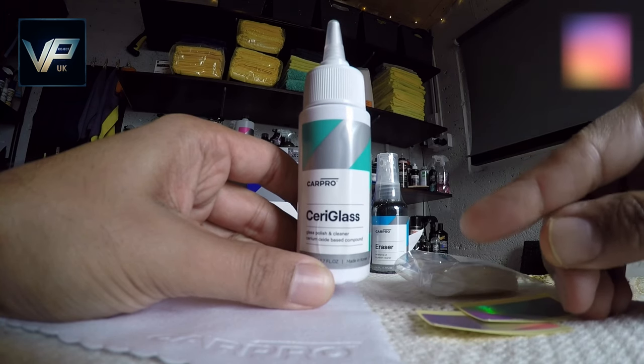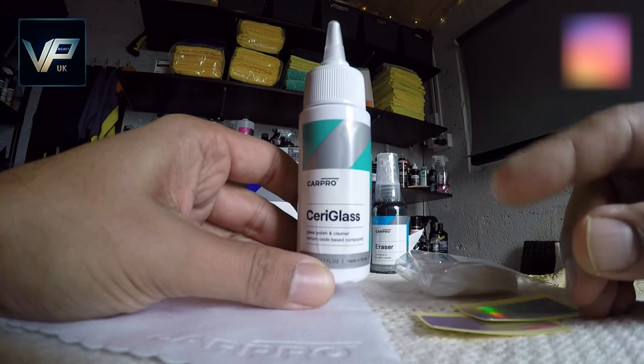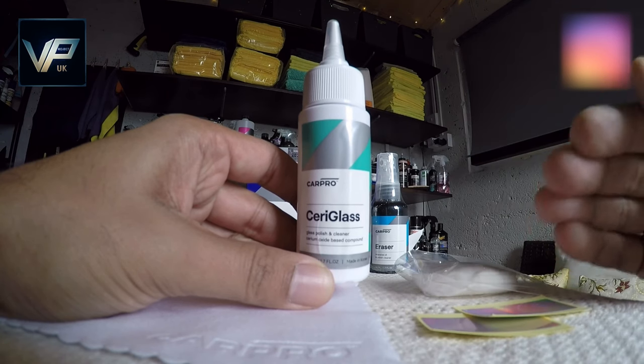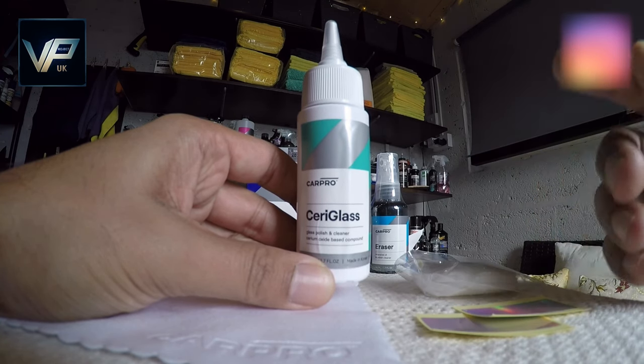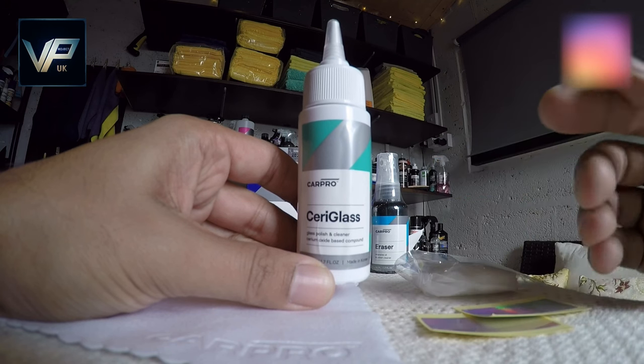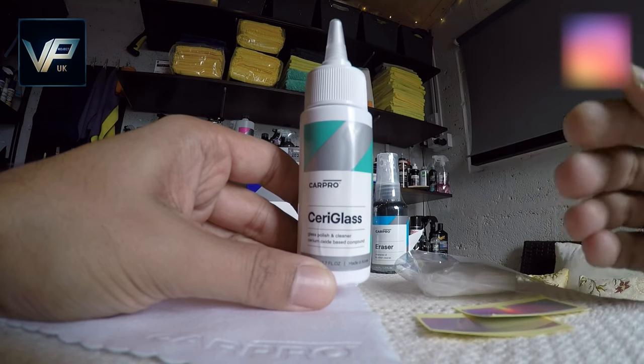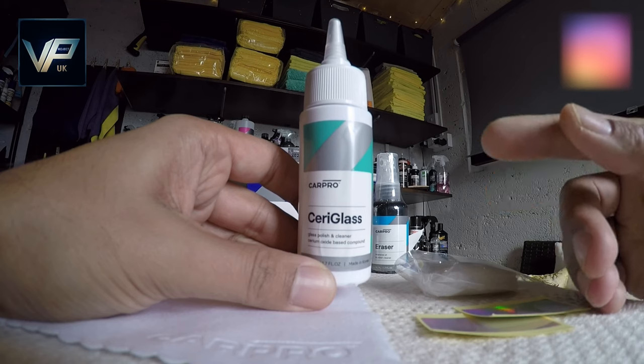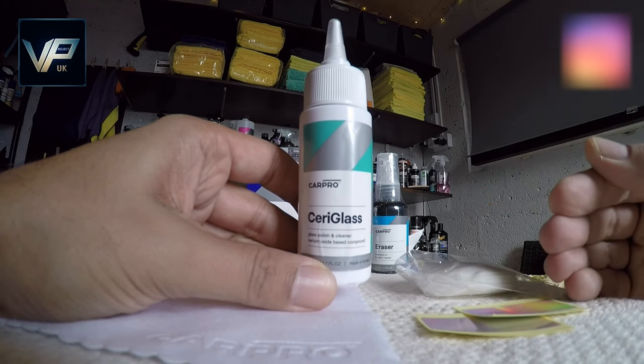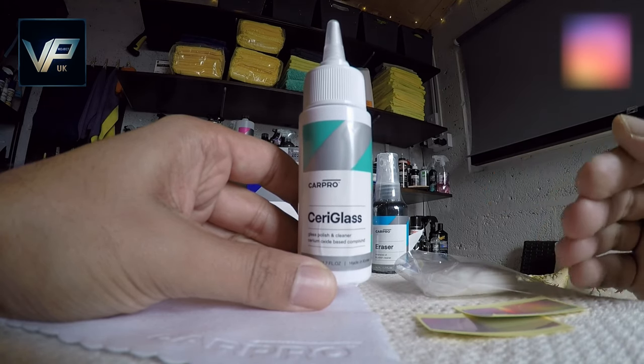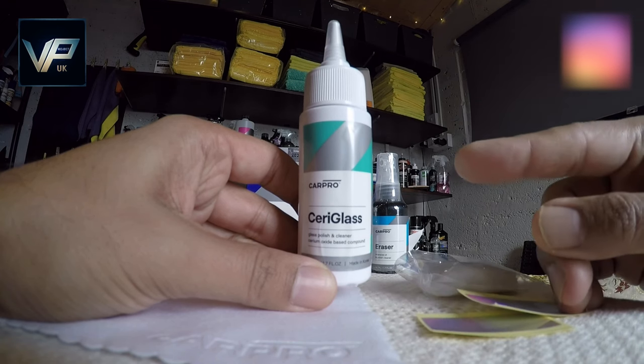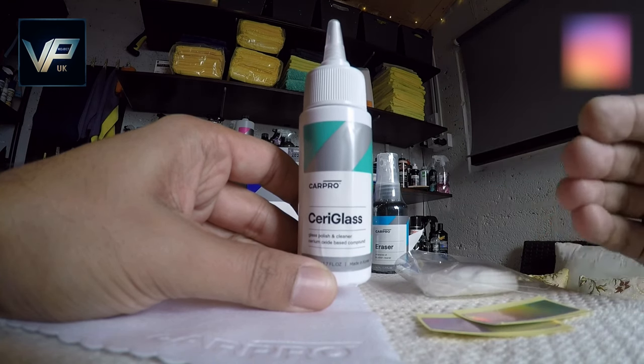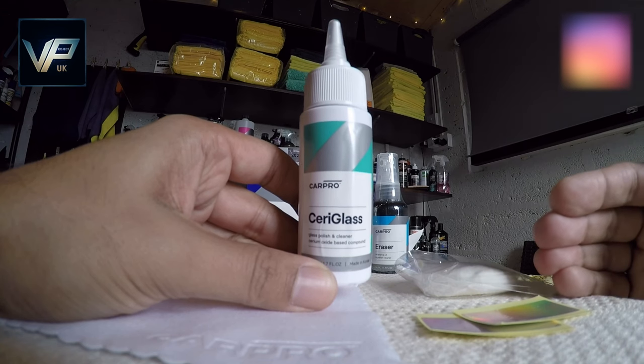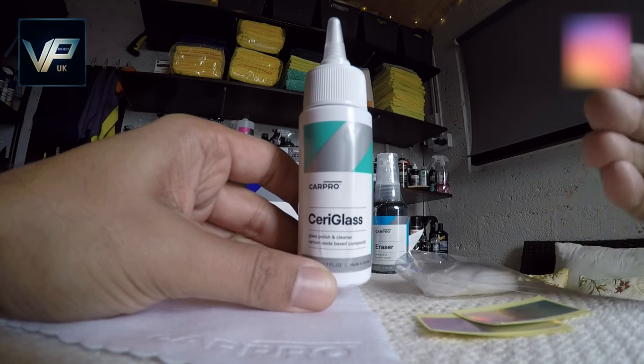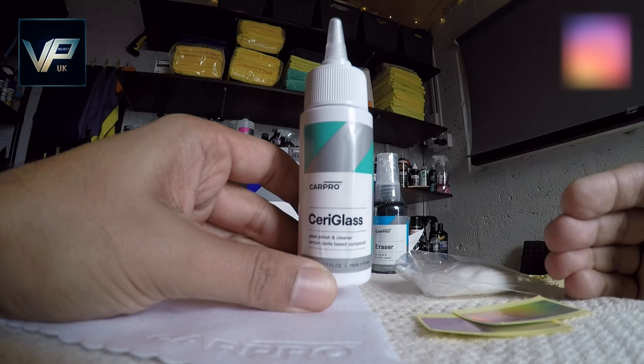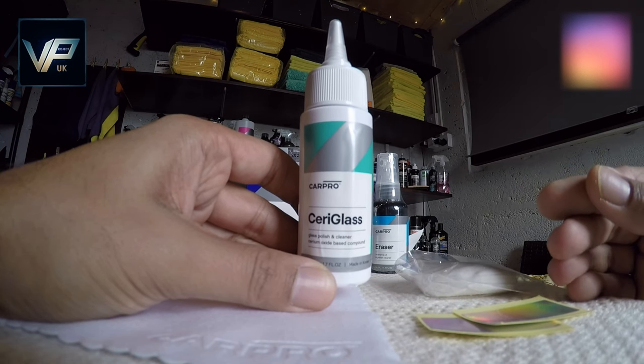However, CeriGlass is capable of removing any layers you might have on your glass. So if you've got any protective layers, we would not recommend using CeriGlass, because that will actually remove it. And sometimes that can actually remove the protection on your glass. So you need to make sure what type of glass you have. Does it have some form of protective film on it? If it does, don't use CeriGlass. Use another lighter glass polishing compound, something like Meguiar's glass polishing compound, something similar which is not cerium oxide based, because this can be quite aggressive.